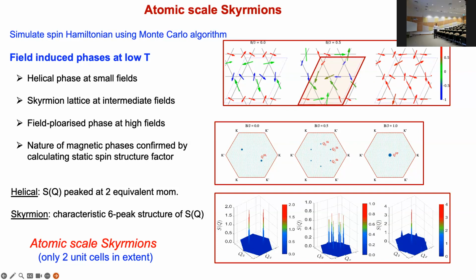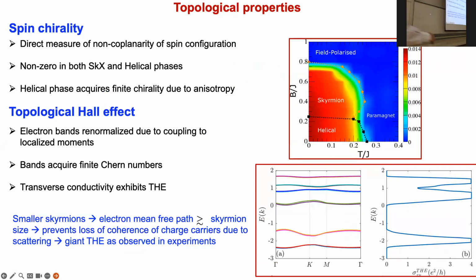It's interesting to note that the size of the skyrmions is only 2 unit cells big. So this is a breathing Kagome lattice. In a Kagome lattice, each unit cell consists of 3 sites. This is a breathing Kagome lattice, which means there are these 2 inequivalent triangles. So the unit cell consists of 6 sites, and here the skyrmion size is only 2 unit cells big. Now we calculated the spin chirality, which is shown schematically here. The spin chirality is finite in the skyrmion phase, but also finite in the helical phase because of this anisotropy that we have included.